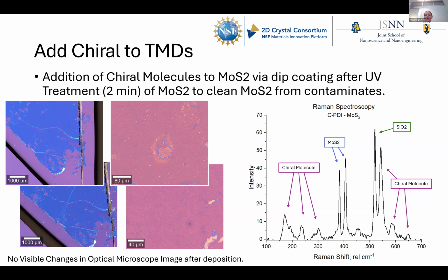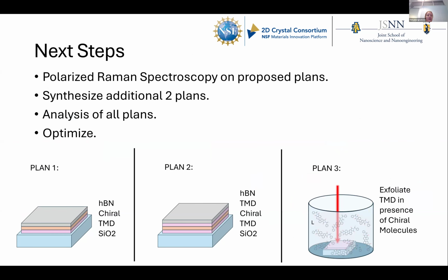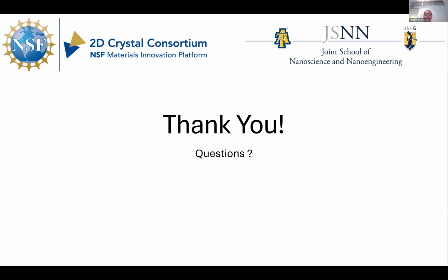And then for the Raman, before was just the MoS2 peaks, but now we can see the Raman has the chiral molecule peaks that were shown in the preliminary work, and then the silicon peak that was not there because the chiral molecules were sitting on glass before. And these are all the labeled peaks. My next steps will be to do polarized Raman spectroscopy on this system, and then do the other two plans, plan 2 and plan 3, and then analyze everything and optimize it. I did not add an acknowledgement slide because I forgot, but thank you. Do you have any questions?